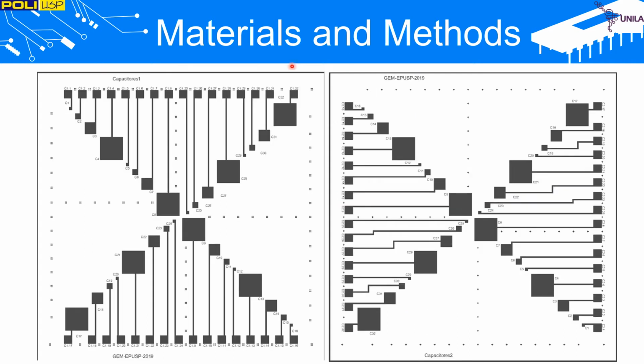Photomasks for patterning both bottom and top capacitor electrodes are shown in the following figures. It has 32 capacitors whose areas are defined by the overlapping of squares with size of 25, 50, 100 and 200 micrometers.